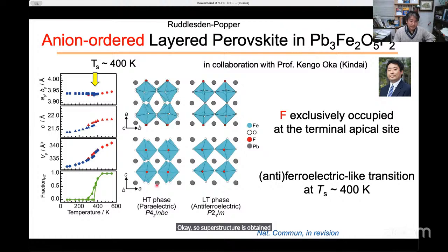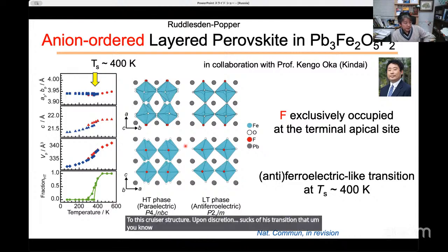But anyway, this material has this type of octahedral tiltings. But at 400 Kelvin, the structure phase transition occurs from this crystal structure to this crystal structure. And upon this structure phase transition, the superstructure vanishes. But as you can see, here the octahedral shapes are pretty distorted. The high temperature phase is of course also distorted, but much less. Okay. But here, there's a large shift of the central iron species, which is trivalent anyway.